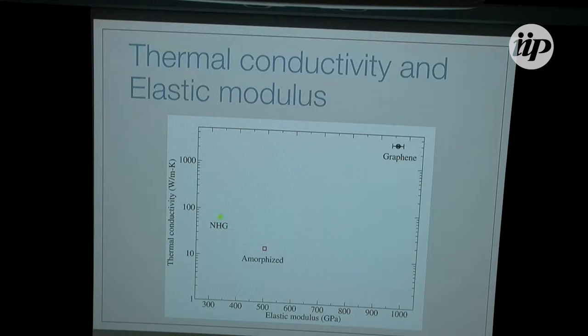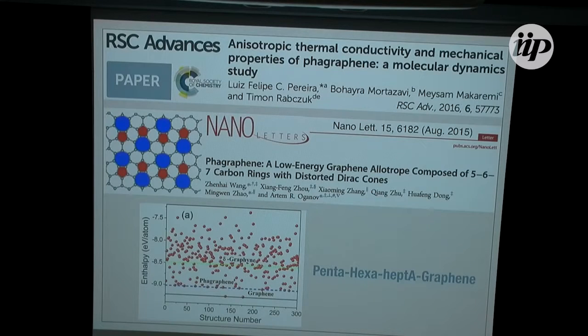When we calculate the elastic modulus and the thermal conductivity, nitrogenated holey graphene is here in our graph. It has a not so low thermal conductivity and a low elastic modulus, compared to amorphized graphene, which has a high elastic modulus but a low thermal conductivity. You could choose either one, for example, if you wanted to reinforce a polymer and make it stronger but not a good thermal conductor, or you want it to become a thermal conductor but you don't care about the mechanical strength.